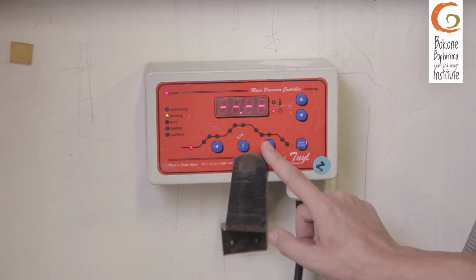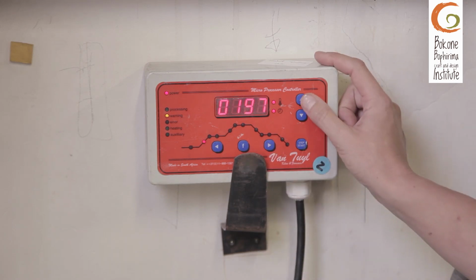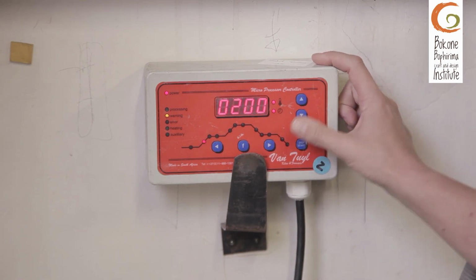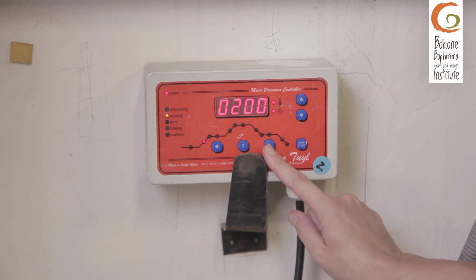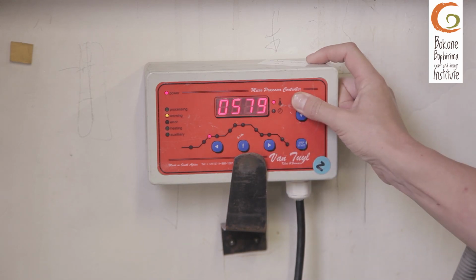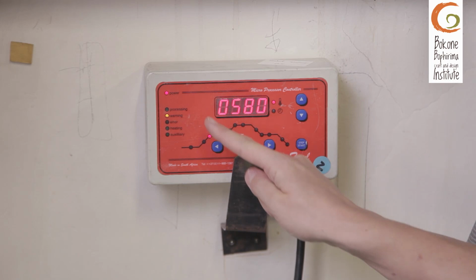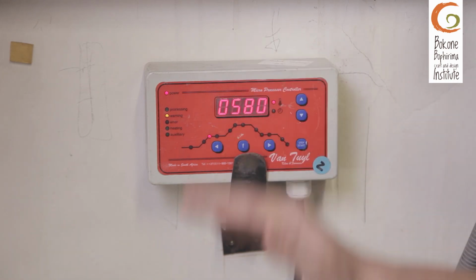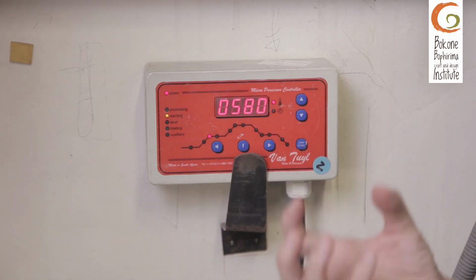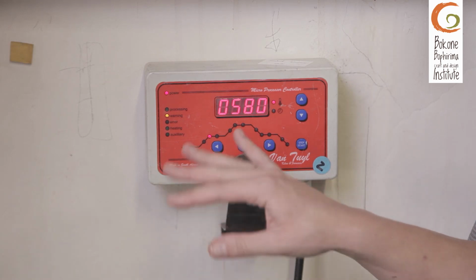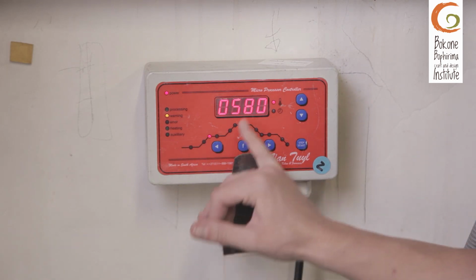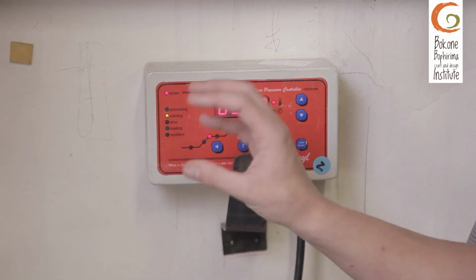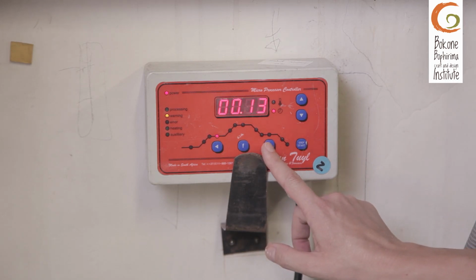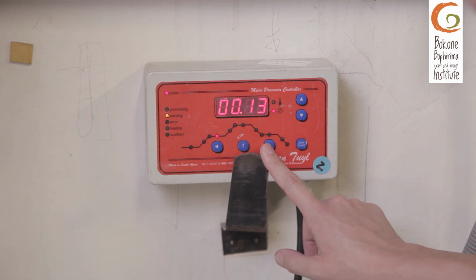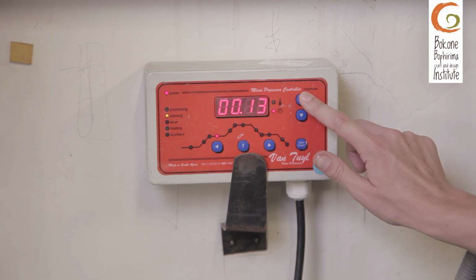We're not going to delay it. We're going to start the process immediately, and we're going to take it up 200 degrees an hour, so still quite slow in glass, up to 580. Once again, 580 is our point. Anything below 580, our glass is fragile, so we need to make sure that we are quite delicate with our glass in this process. We are then going to hold it there for 20 minutes.